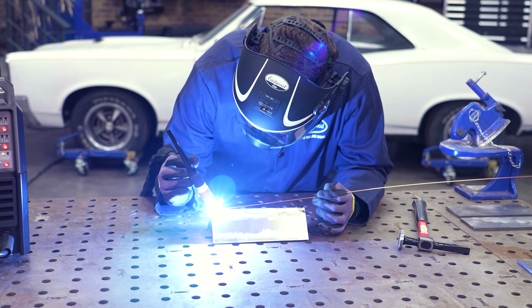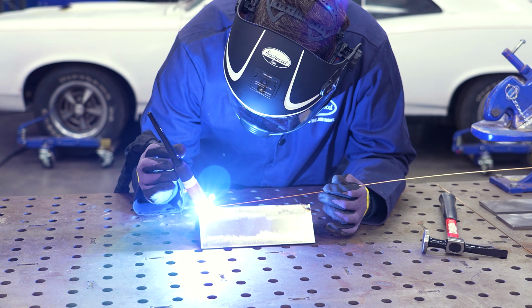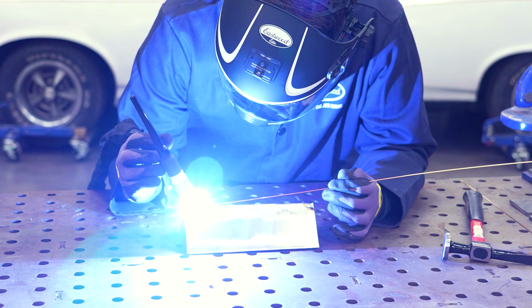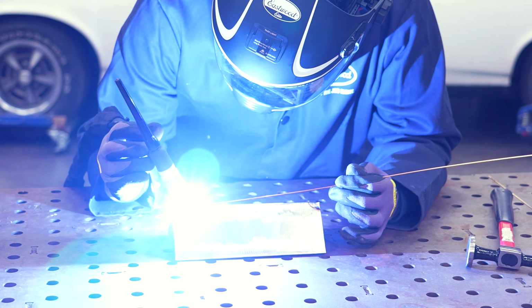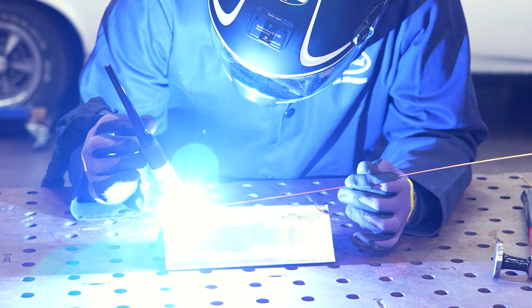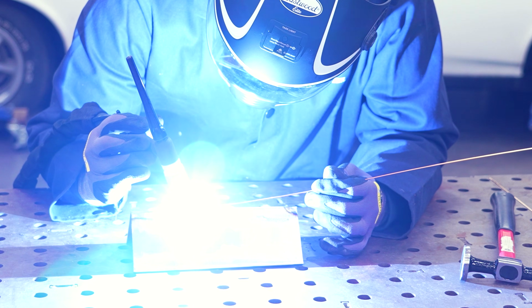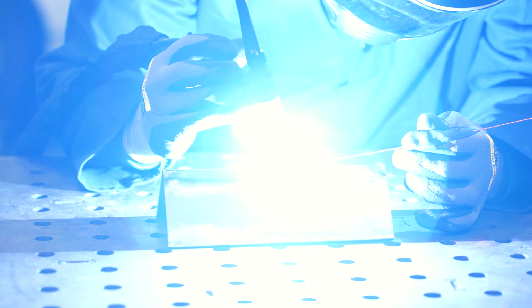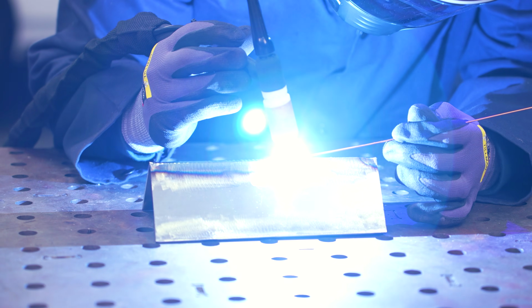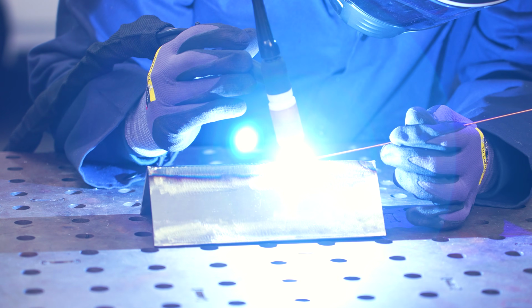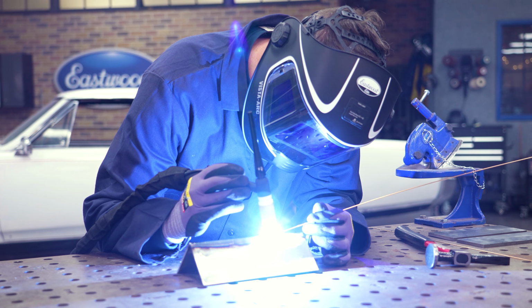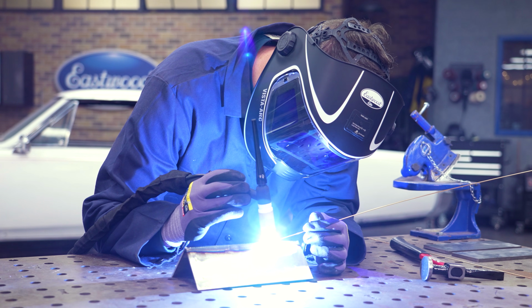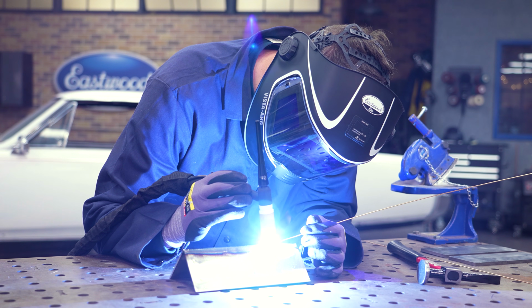So just like before, I'm gonna travel with the pulse here, go to the front of the puddle each time. What you can do on like heavier stuff like this, is you can actually just lay your filler rod there. Don't have to worry so much about dipping it. Peak, move, peak. If you were working with stainless, using pulse is your friend because stainless is often thin, but also stainless is prone to sugaring and becoming compromised if you get a little too hot. So pulse will help mitigate that heat. This is mild steel, so I'm not super worried about that, but something to keep in mind.